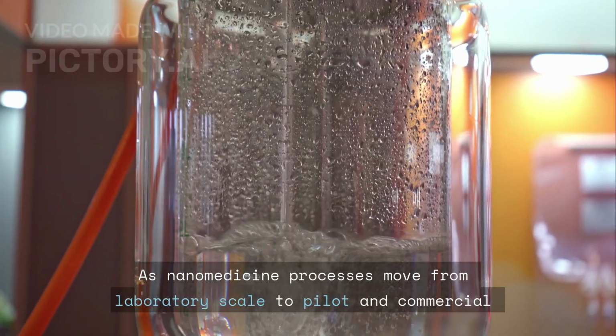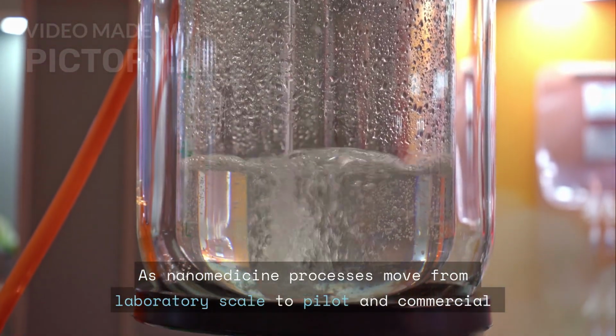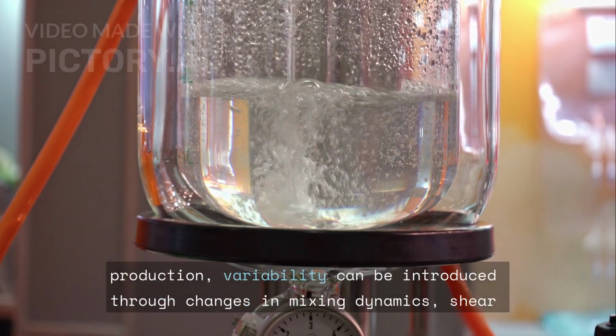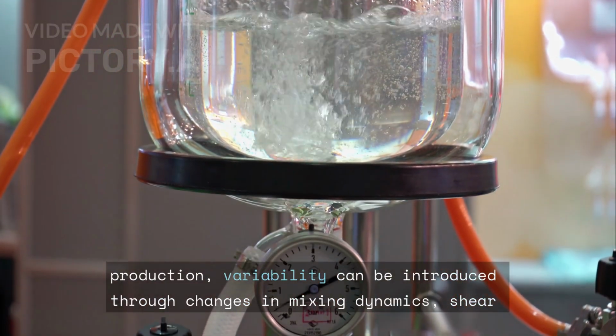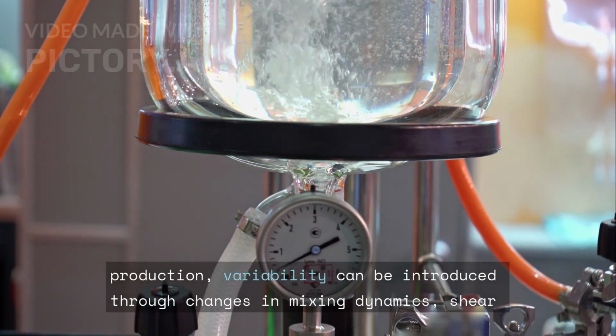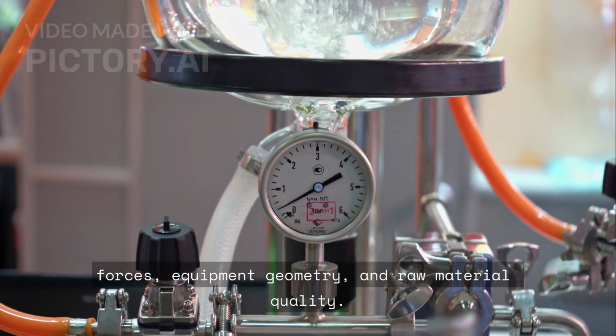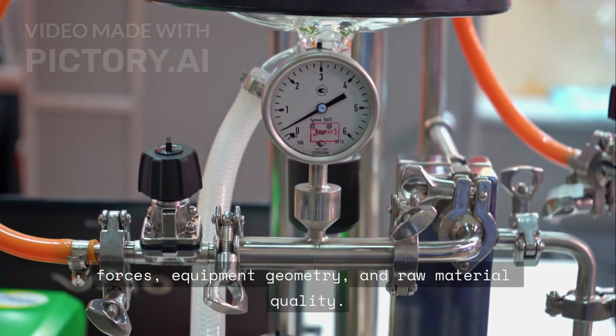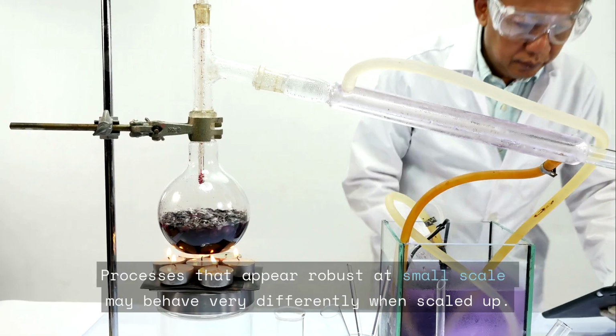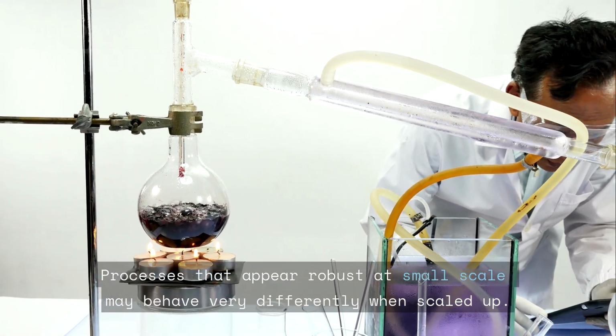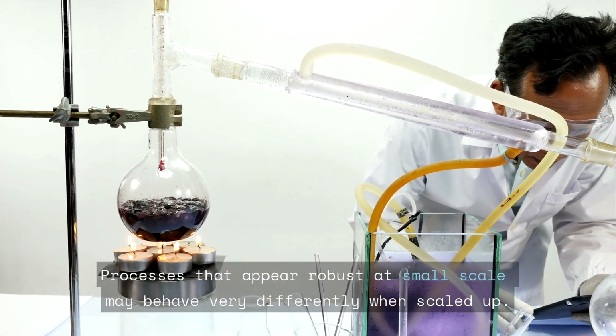As nanomedicine processes move from laboratory scale to pilot and commercial production, variability can be introduced through changes in mixing dynamics, shear forces, equipment geometry, and raw material quality. Processes that appear robust at small scale may behave very differently when scaled up.